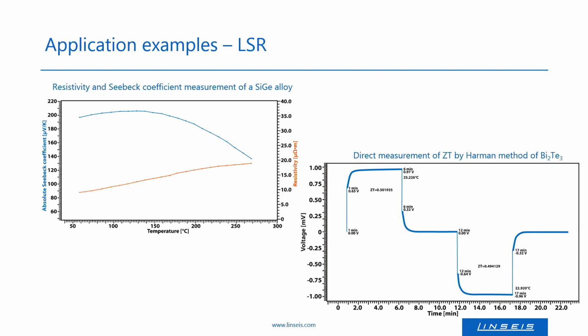So this bismuth telluride sample, it is a NIST certified material. We use it as a reference material, and here one can see the typical voltage distribution at a single temperature measurement point. In this case, the figure of merit value was recorded at room temperature. And here one can see that the figure of merit was determined to be about 0.5, which is the literature value for bismuth telluride at room temperature.